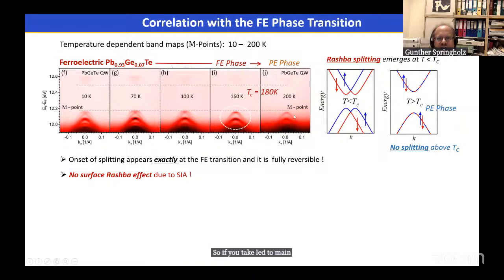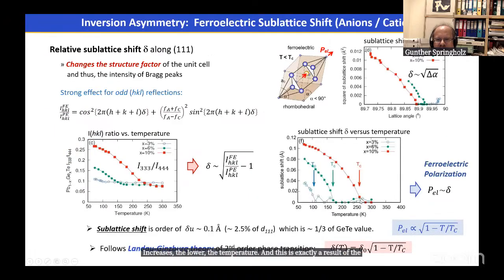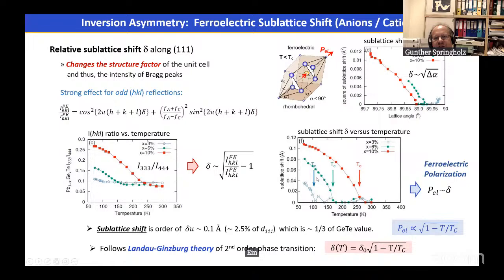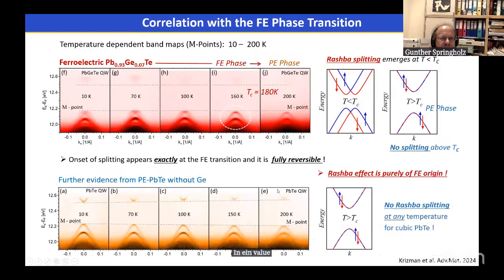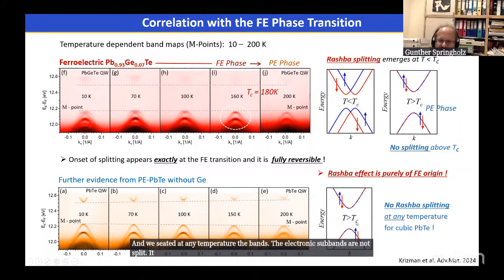So if we take lead germanium telluride above 200 Kelvin, there is no Rashba splitting of the valence and conduction band. Then when we cool down the system, there is the emergence of the Rashba splitting, and the Rashba splitting increases the lower the temperature. And this is exactly a result of the fact that as the temperature decreases, the ferroelectric polarization and the sublattice shift increases and saturates at low temperature to this delta zero value. And again, we can compare this with paraelectric lead telluride, which has no ferroelectric phase transition. And we see that at any temperature, the electronic subbands are not split, meaning that these bands are not spin polarized at any temperature.